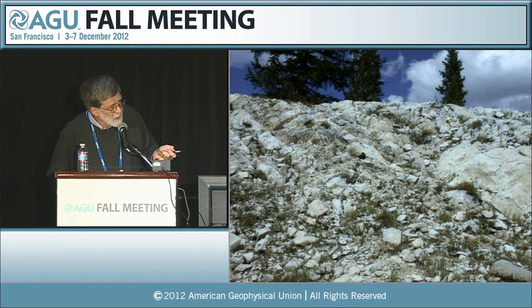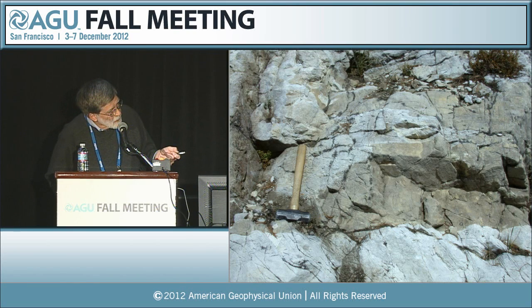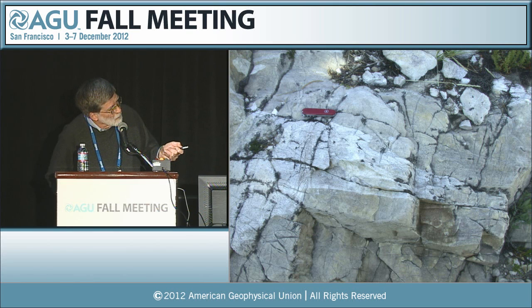Just to quickly show you a couple of pictures. Here's an outcrop. The buff-colored, darker things are the residual dolomite. The lighter, whiter zones are the Periclase marbles. If we get closer, here we see Periclase marble thinning along what's a fracture set into the darker dolomitic marble. Here's a closer view of that, and you can see these are coming down to thinning fracture tips. Here's a tip of Periclase penetrating and replacing out into the dolomite, and there's an even thinner one here. This actually continues; you can't see it very well here, but it continues off several centimeters beyond there.